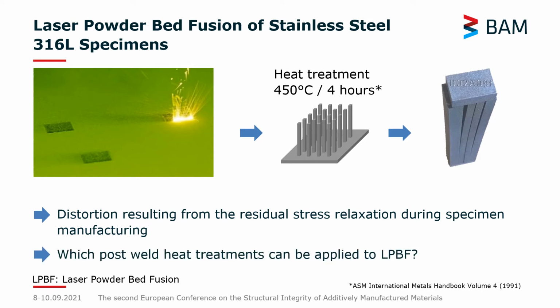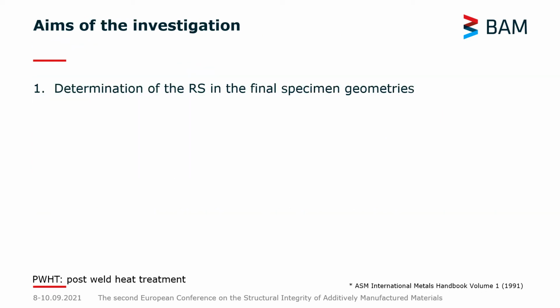And also, what other post-weld heat treatments can be applied to laser powder bed fusion? So what do we know from welded austenitic steels with respect to stress relieving heat treatments that we can read across to the laser powder bed fused parts, having in mind that they have completely different microstructures? This brings me to the aims of the investigation.